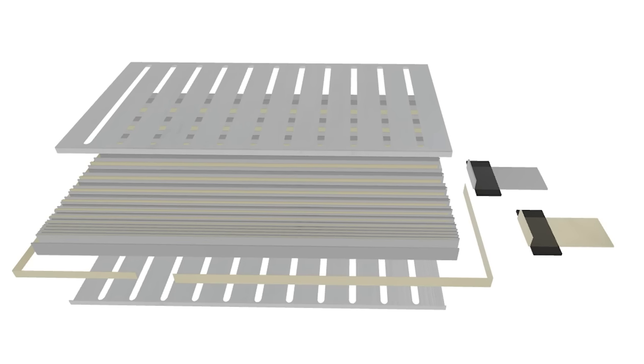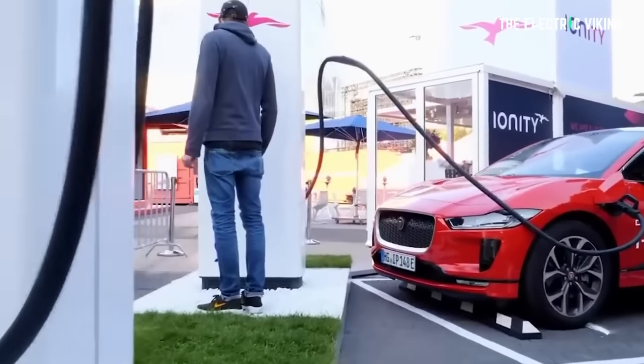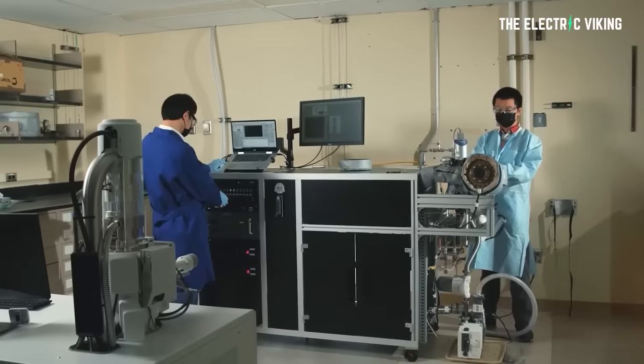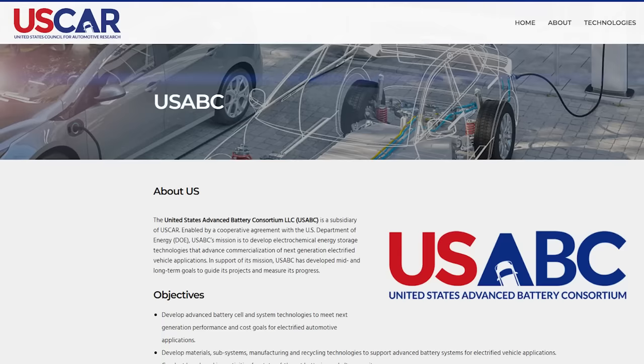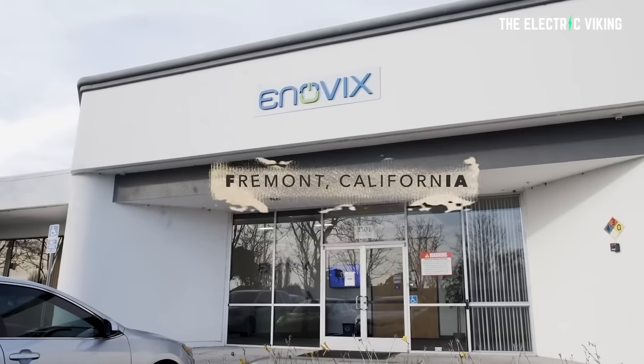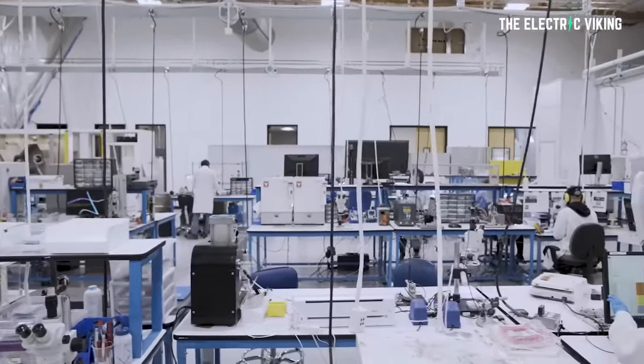There's a California-based company called Enovix, and they're saying some interesting things. Their new type of silicon anode lithium-ion battery could be the solution the EV market is waiting for, as it can apparently charge from empty to full in less than 10 minutes. The battery also maintains 93% of its capacity after 1,000 charges, and it was minimally affected by six months of operation at high temperatures, the company claims. Per the USABC, a battery that can reach 80% charge in 15 minutes and handle at least 1,000 charging cycles can be called advanced — and by that standard, Enovix has accomplished goals that the USABC considered mid to long term.